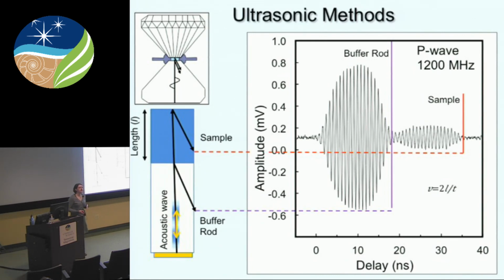This is effectively the same as seismology. The thing that we measure here directly is the amount of time it takes a wave to travel through a material. So this is the setup. What we do is we generate an acoustic wave that travels, in this case, through a buffer rod and then into the sample. At every interface, part of the wave is reflected and part of the wave is transmitted. And so that's what's shown here, where we have the waves as a function of time.